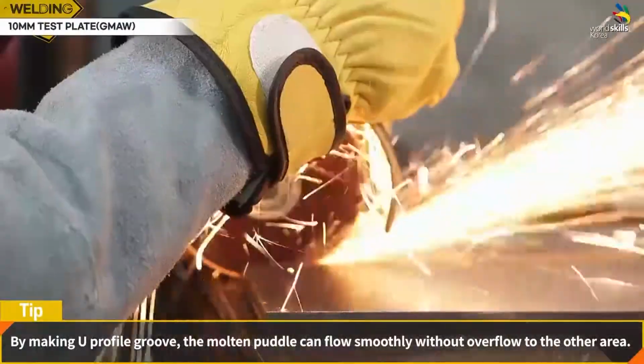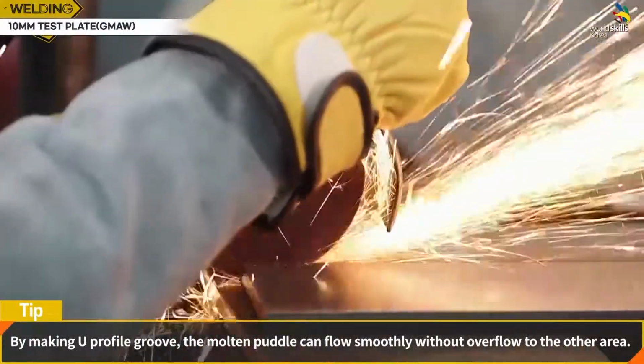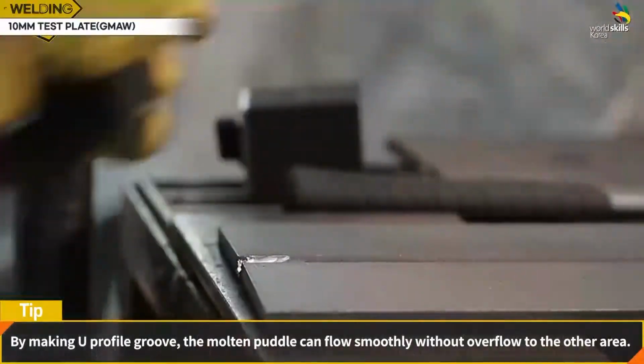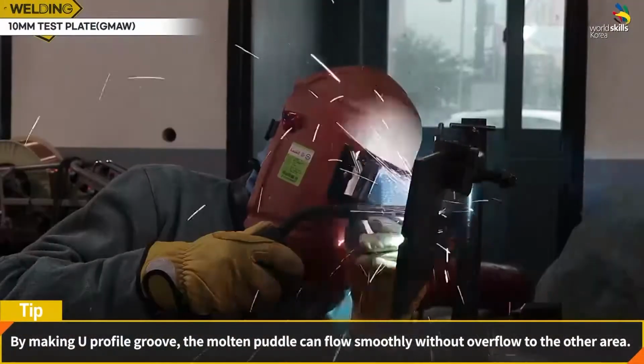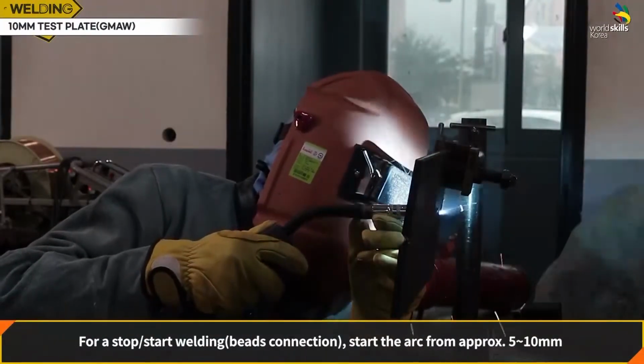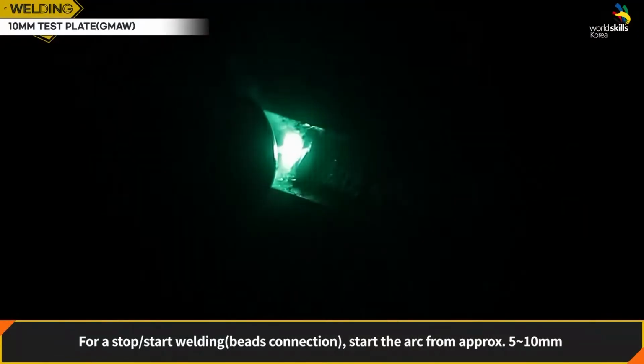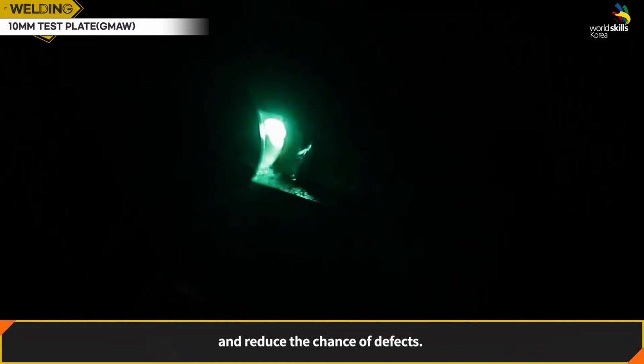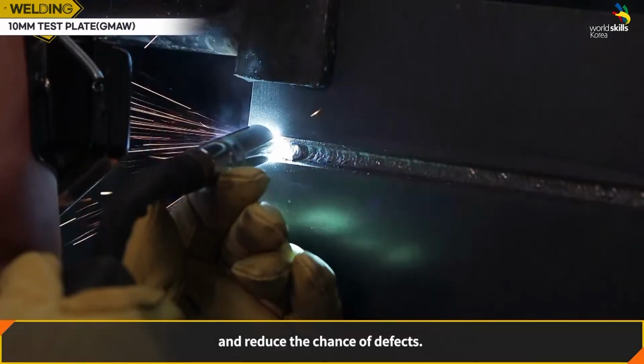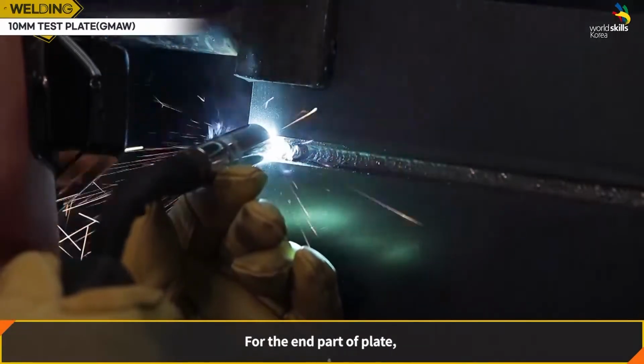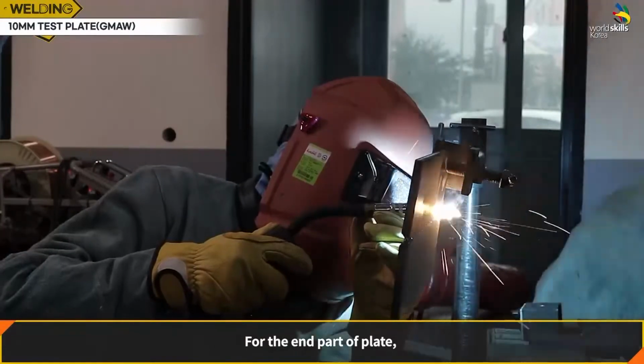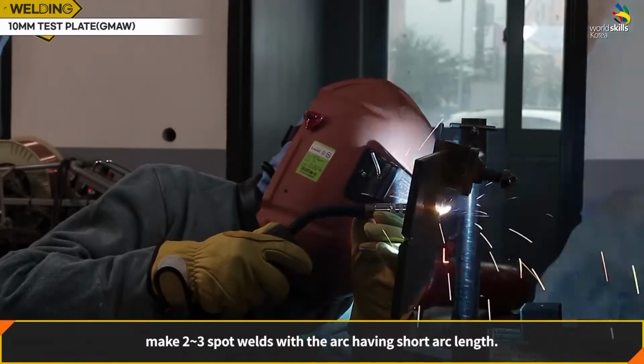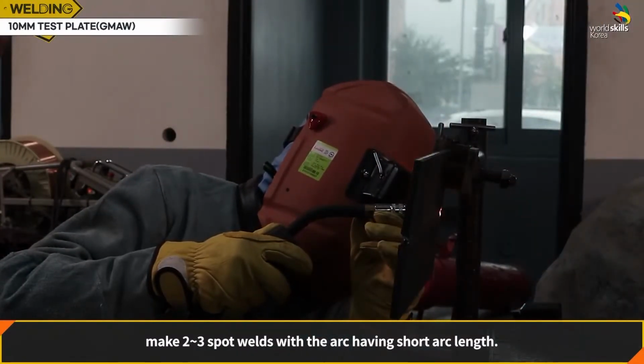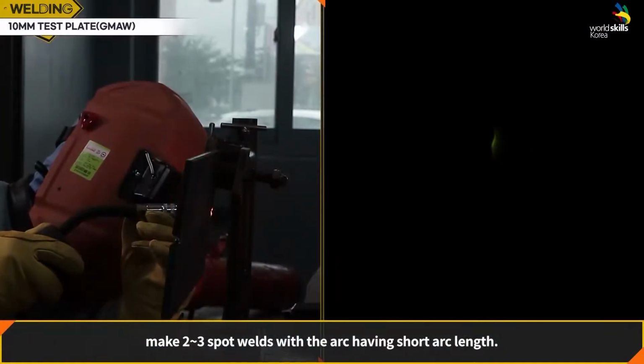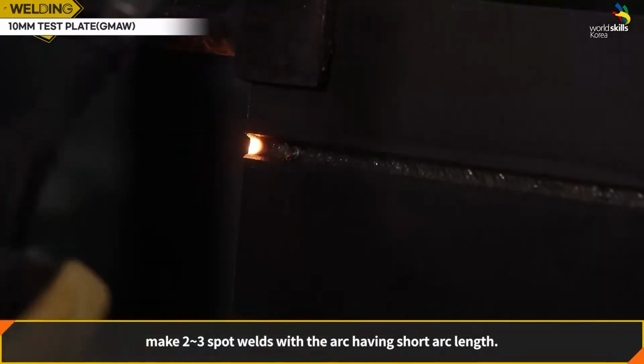By making a U-profile groove, the molten puddle can flow smoothly without overflowing into other areas. For stop-start welding and bead connections, start the arc approximately 5 to 10 millimeters back from the finished location to make a smooth transition of welding beads and reduce the chance of defects. This is the endpoint processing of the root pass. When reaching the end of the weld, keep the arc length short and finish with 2 or 3 spot welds.